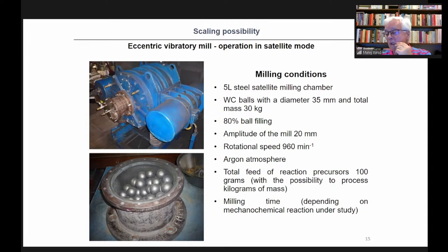The amplitude of this mill is 20 millimeters. And I have to say this is one of the main technological advances, because in vibration mills, this amplitude is up to 12 millimeters. So this is more intensive. And another difference is that if you apply a normal vibration mill, you apply only circular motion of the mill chamber. In our case, there is a combination of elliptical, circular, and linear vibration. And all of these effects altogether give rise to the results.